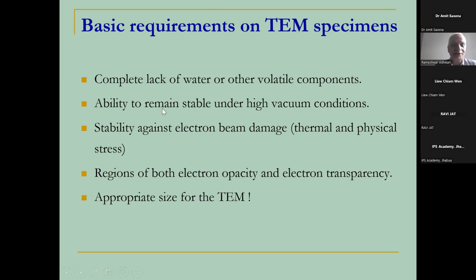Then these specimens should be able to be stable under high vacuum conditions, because the electron microscope system is put in high vacuum condition. At the same time, the samples, the specimen, should be stable against electron beam damage. There should not be any thermal stress, neither should there be any physical stress.